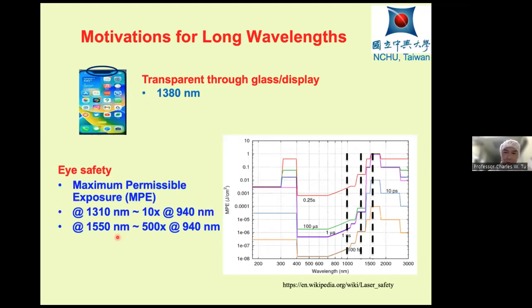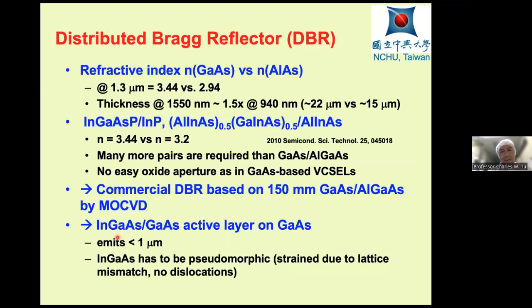But to go to 1550, the problem is that it's not very practical, because you have to grow on an indium phosphide substrate. Unfortunately, for the indium phosphide-based material, the refractive index difference is not too large, 3.44 versus 3.2, whereas for gallium arsenide, aluminum arsenide, it is 3.4 versus 2.9. So on indium phosphide substrate, you have to grow a much thicker layer. You have to have many more pairs to achieve the same reflectivity. And so the interest is to have this long wavelength emission on gallium arsenide substrate, so that we can utilize the commercially mature DBR technology on gallium arsenide.